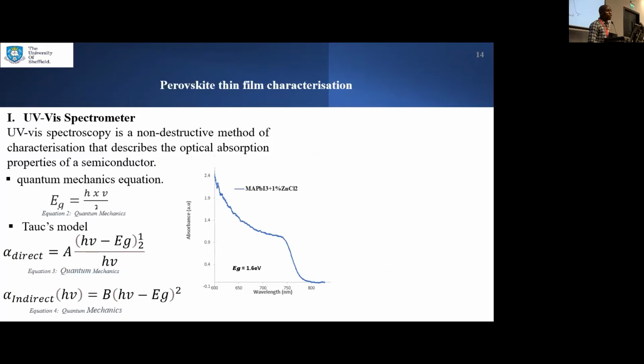Our results, where we used UV-Vis to characterize our materials. Actually, the aim of using UV-Vis was to determine the band gap of our perovskite materials. In doing that, you can use a direct method, using this formula with the energy of light and your Planck constant, and this wavelength is mostly obtained from this edge. When you extrapolate from here, you get your wavelength, and then you do a direct calculation to get your band gap, which is the easiest way to determine the band gap of a perovskite material.